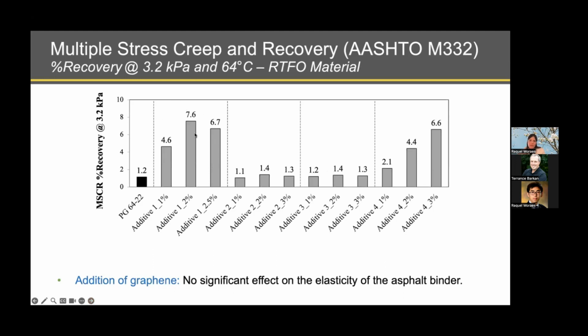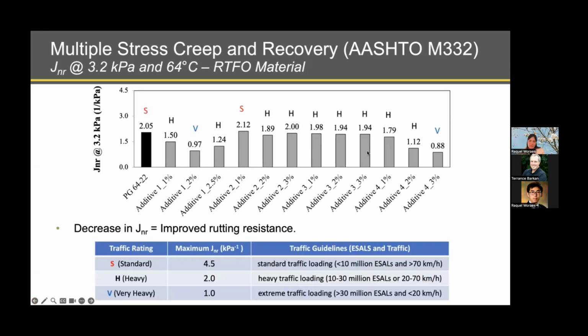We can see that for the additive 1, we saw a slightly higher percentage recovery in comparison to the base binder, as well for additive 4. But this is related to the fact that, as indicated on this previous slide, this specific binder was harder in terms of JNR than the base binder.